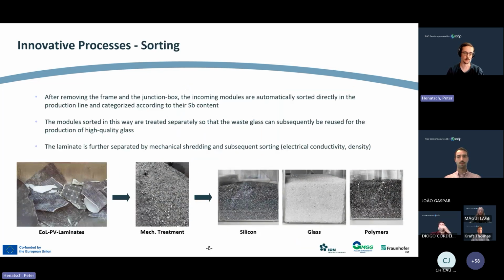In the sorting, we are now removing the frame and the junction box and then shred these modules after they have been tested by our colleagues from IPN for their antimony content. Yes, these laminates or the deframed modules are shredded, and you can see here some fractions will get produced via electrostatic or electrical conductivity separation or density separation. So we can get down to the silicon or the cell fragments at this stage, and some glass particles here are shown, some small particles, but there are also the larger particles from the shredding process and some polymer fractions.